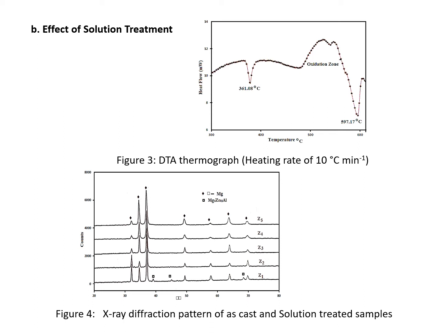It is difficult to identify the other peaks of many possible Mg-Zn alloy phases present in the alloy, mainly because oxidation of this alloy starts above 450 degrees centigrade. Figure 4 shows the XRD analysis of the as-cast and ST samples at 360 degrees centigrade for different intervals of time. It is observed from figure 4 that the complete dissolution of Mg4Zn11Al has taken place after 24 hours of holding.